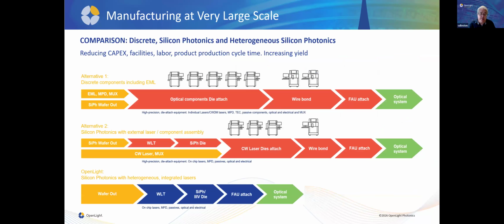As I mentioned a couple of times, the whole point of doing silicon photonics is to get something that works at scale. This isn't just the proposition that you can make devices cheaper. Of course, that's very important as well. But you need to be able to manufacture in the numbers of the millions. The typical way that you do this is you take optical components, you use die attach machines, you wire bond them, you put them on substrates, you attach an FAU piece by piece, which requires a lot of investment in CapEx, and a lot of yield fallout throughout the process. You can only scale this basically by investing in more infrastructure.